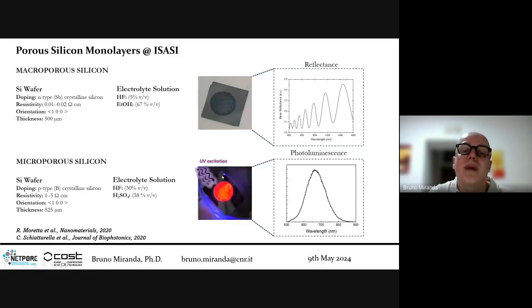And this is the microporous silicon, which is instead photoluminescent. Here you can detach this membrane, sonicate it, so mechanically break this membrane into nanoparticles with controlled size. And this is the typical photoluminescence spectrum that we can measure.